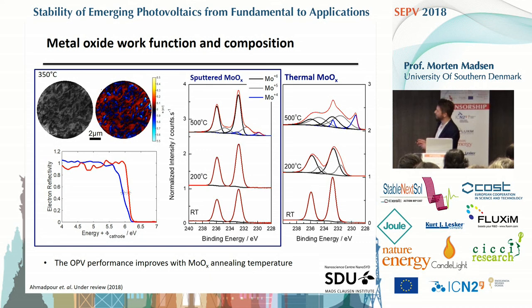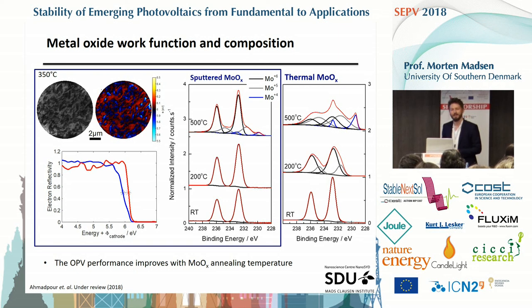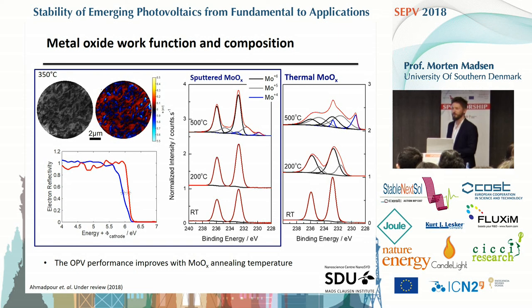One interesting thing we see is that for the sputtered molybdenum oxide versus the thermal molybdenum oxide, we see quite different behavior when we heat them up. Looking at the XPS data for these two films, for the sputtered oxide we can heat it up quite a lot without changing the composition. When we go to very high temperatures, we see a slight reduction in the oxide, but it's not a lot. These films seem to form crystalline layers and are quite resilient towards heat treatment and annealing. The opposite is the case for the thermally deposited molybdenum oxide—when we heat this up, we already at low temperature start to reduce the metal oxide. This is done by vacuum annealing, and we lose oxygen when we heat it up.